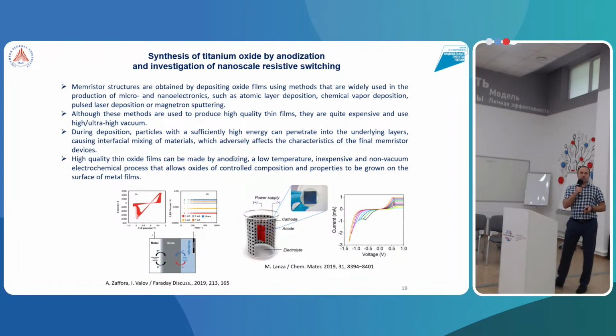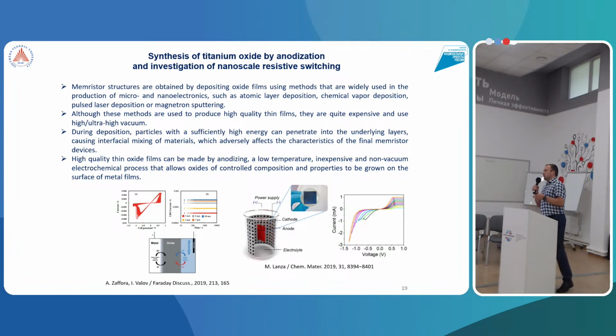I want to shortly show you our results produced in our lab. One of the technologies we used, the first technology we used to produce memristive materials, is the electrochemical technology, which has some advantages. Anodization is produced at low temperature, an inexpensive and non-vacuum process that allows oxides of controlled composition and properties which can be grown on the surface of metal films of different metal elements.